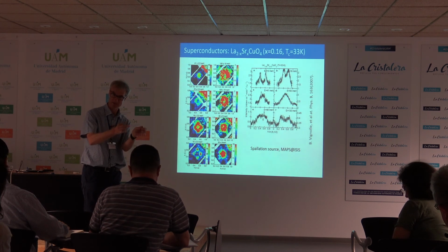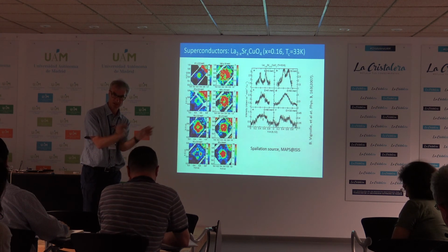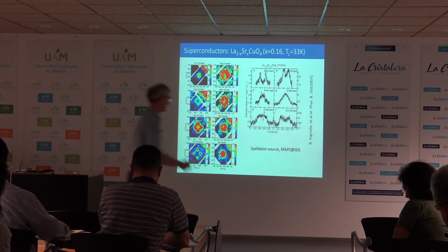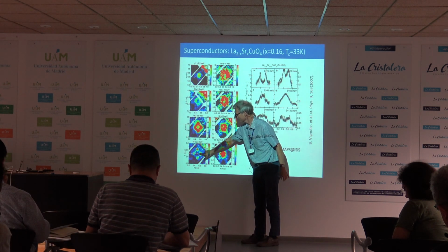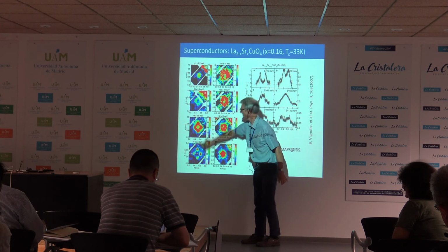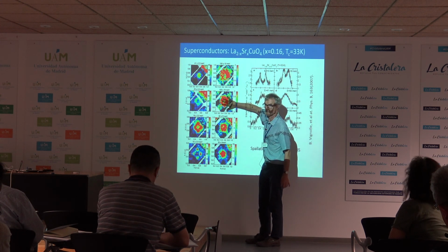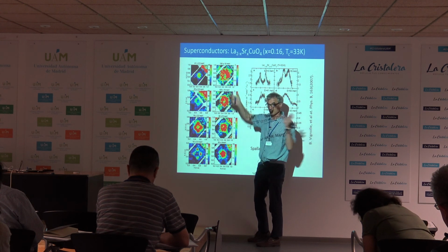And to say they have a large correlation length isn't really the point. It's the width of the excitations at low energies that is small, and that corresponds to a large length scale. So this peak here, for example, this peak in Q, that's at 10 millivolts. It's quite small, whereas this stuff here, if I convert it to a length scale, is much shorter.